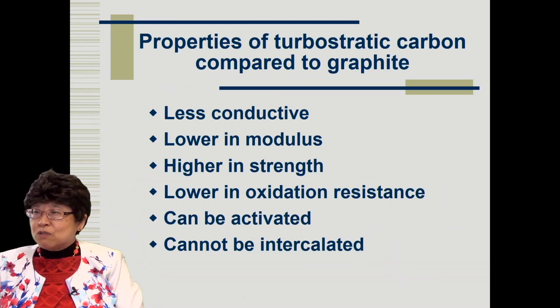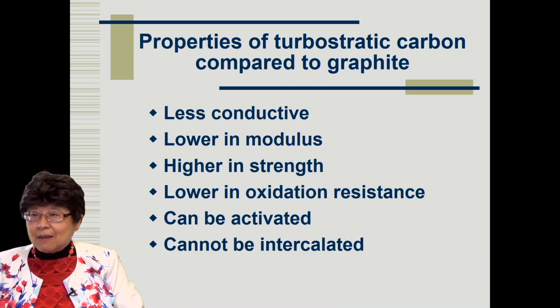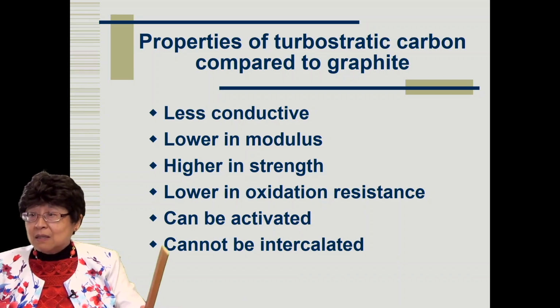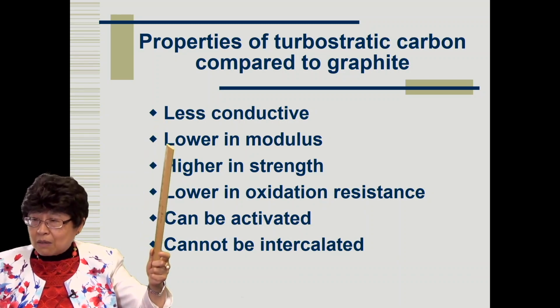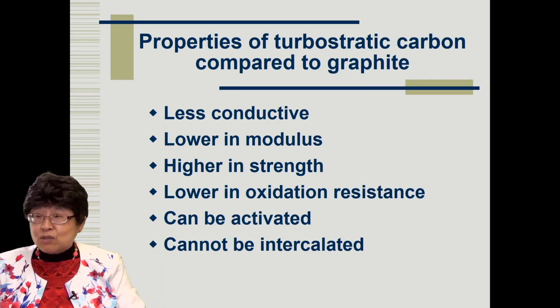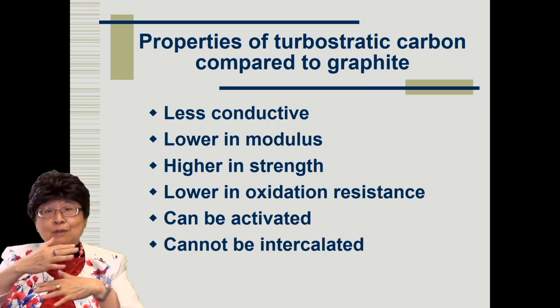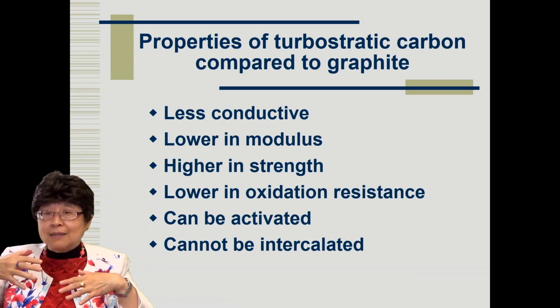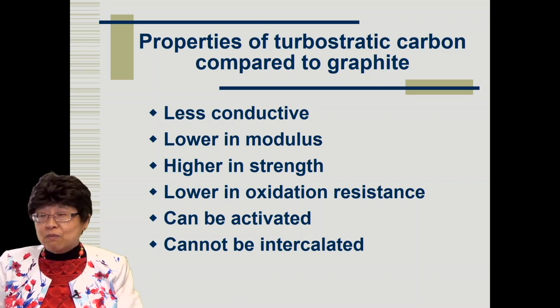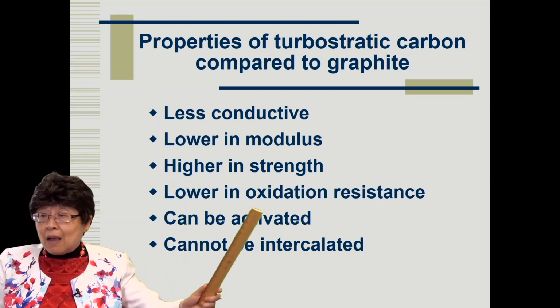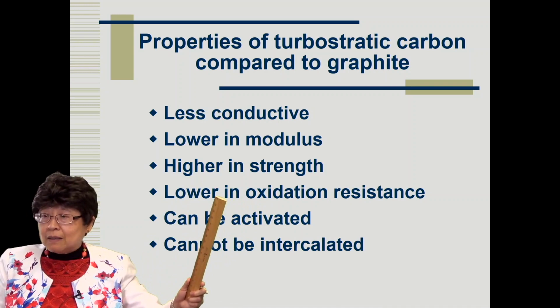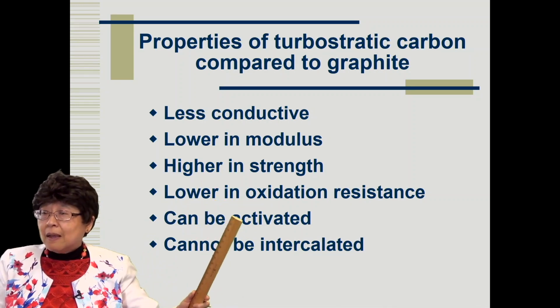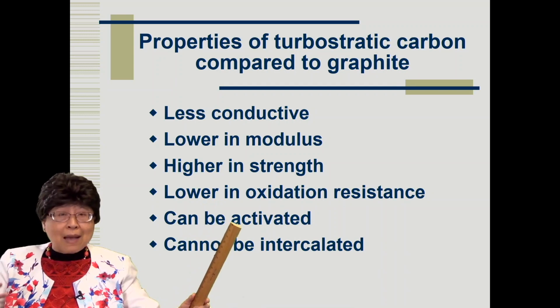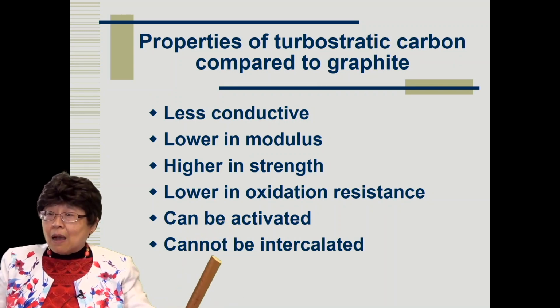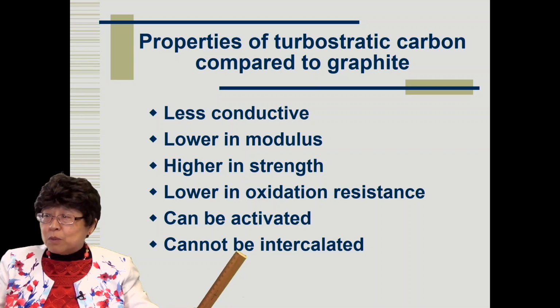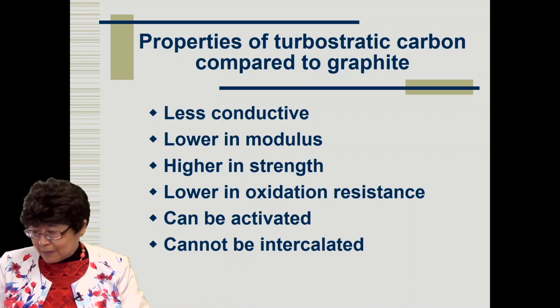The properties of turbostratic carbon are quite different from that of ideal graphite. They are less conductive, lower in modulus, but high in strength. The high strength is because the layers are not so flat, and so it's harder for the layers to slide with respect to one another. And the turbostratic carbon is lower in oxidation resistance than the graphite, but they can be activated to form activated carbon more easily. And the turbostratic carbon cannot be intercalated.